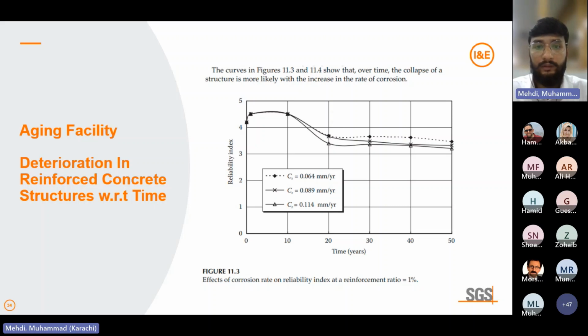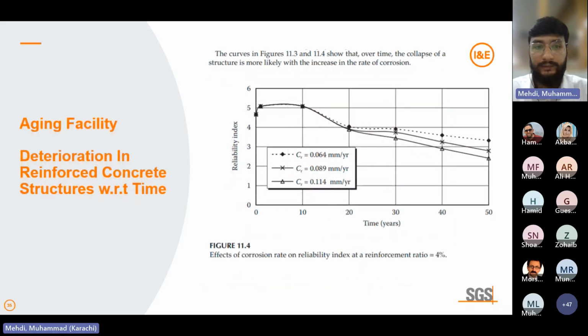In this graph, you can see that in the 0 to 10 years pattern, we have a reliability value of 4 to 5, then from 10 to 20 years it reduces, and then from 20 to 50 years it is constant. But in the next slide, you can see that if the reinforcement ratio is increased to 4%, then from 0 to 10 years the reliability is again more than 4, in fact more than 5, which means the reliability is improved. But from 10 to 20 years it reduces, and after 20 to 50 years it reduces gradually, and it is not a constant curve.